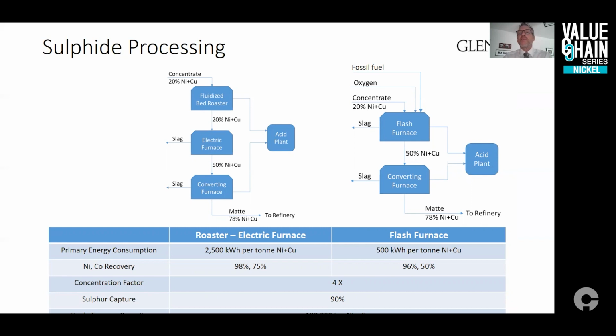In this furnace, air is injected into the molten matte to further oxidize iron and sulfur. Converting is also autogenous. The final matte typically contains about 78% nickel plus copper plus other byproducts, up to 2% iron, and around 20% sulfur.